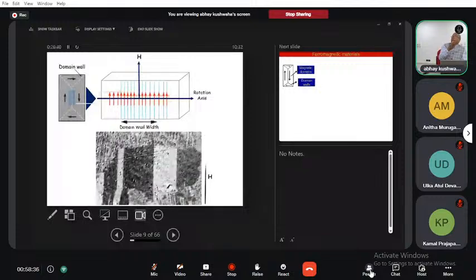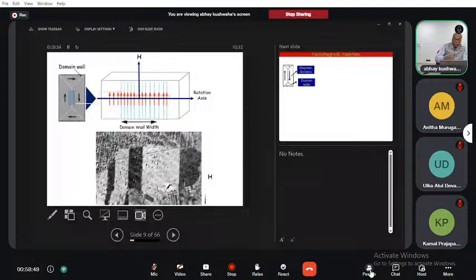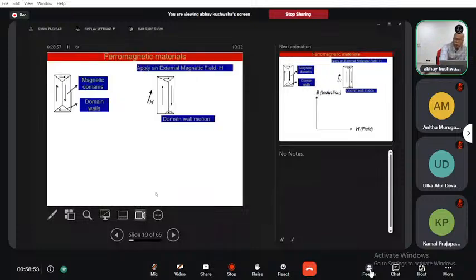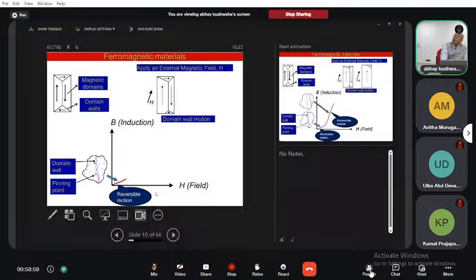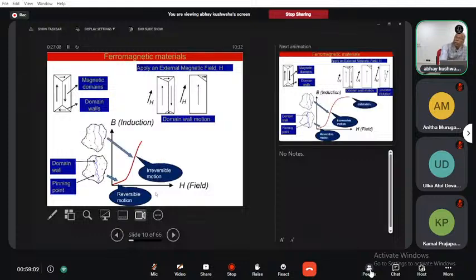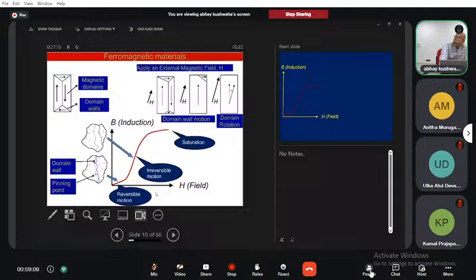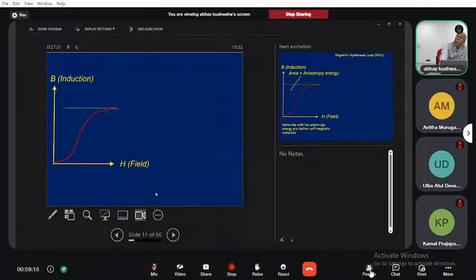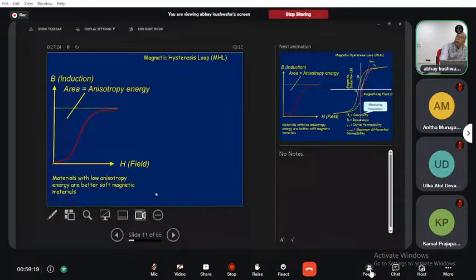So the domain wall moves from one position to the other position, and when it is getting the saturation, all the moments are oriented in one particular direction. So if we plot this magnetic field versus the induction, at the initial stage, which is called the reversible motion of the domain, then we have the irreversible motion, and then it gives the domain rotation, and we got the saturation. And if we go for the complete cycle, then this area is called the anisotropic energy of the material.